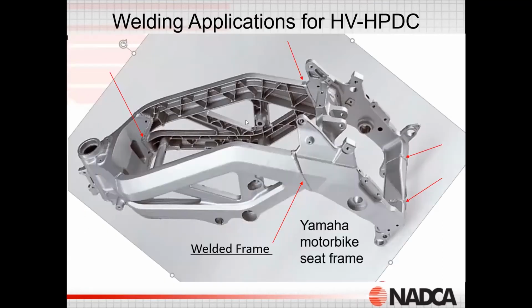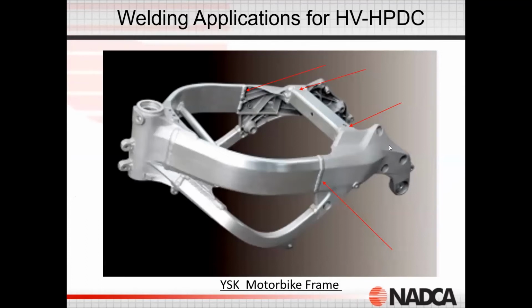Along with riveting, the other joining methods are welding. So we're welding high vacuum, high pressure die castings together. So in the past, when you try to weld just a standard die casting, that weld is going to fail. It's not going to give us a good weld. In this case, we're now welding different die castings, two different die castings, or we're welding die castings. So this piece and this piece are die castings, and we're welding those to different types of materials. So we've got either hydroform or extruded aluminum that's being welded to a die casting here and a die casting here.